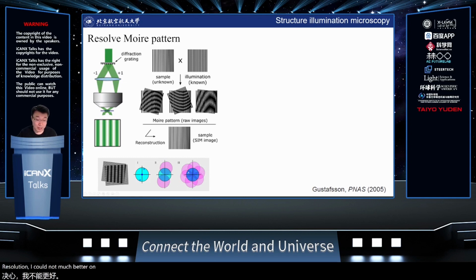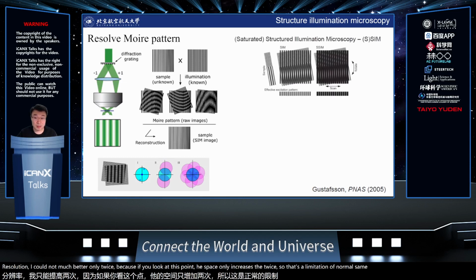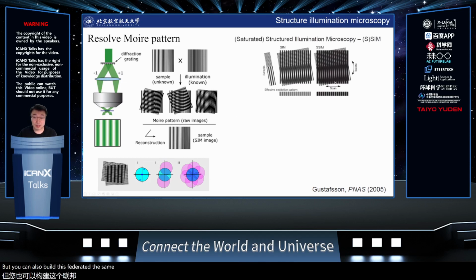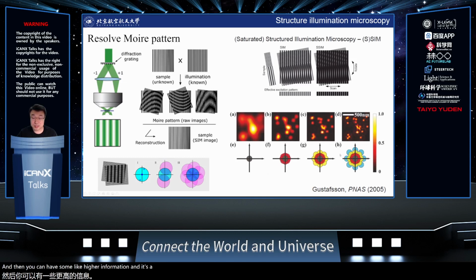Actually, not much better, only twice, because if you look at K space, you only increase it twice. So that's the limitation of normal SIM, but you can also build saturated SIM. What I mean is if you shine the pattern and increase the power, your response is going to change, and then you can have some higher-frequency information. By further increasing your power and doing many directions, you can solve this and have much better resolution. But the challenge is similar to STED. If you want to give some saturation, you have to use really, really high power. And remember that in this situation, we are using wide-field excitation, so you need extremely high power to do that.